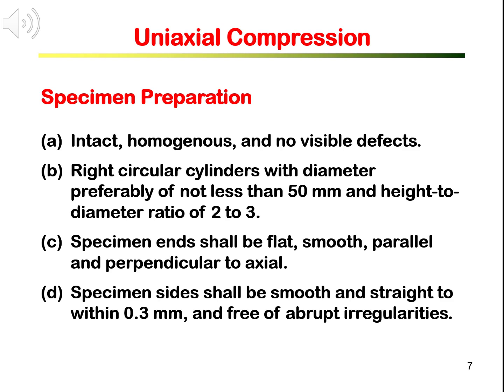The two ends of the specimen must be cut and ground to be flat, smooth, parallel, and perpendicular to the specimen axis. The sides of the specimen should be smooth and straight within 0.3 mm tolerance, and there should be no visible irregularities such as voids and pores.